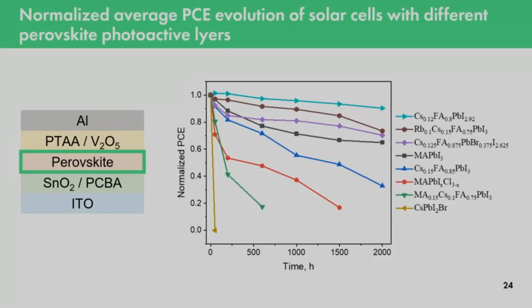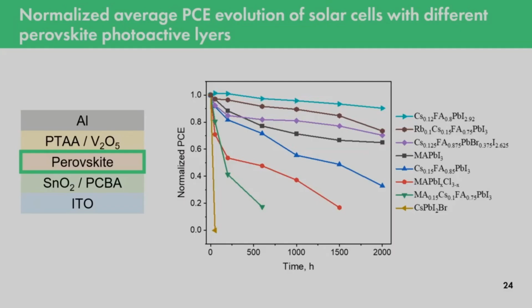Thank you for this question. Actually, these two materials, which are really separated in this rating, have a very drastic change in their chemical composition, because as you can see, the bottom one, cesium 0.15, then formamidinium 0.85, lead iodide 3, is a completely stoichiometric material, which fully corresponds to the formula ABX3. And if we look at the top one, it's cesium 0.12, formamidinium 0.8, and then lead iodide 2.92. This material is non-stoichiometric, as there is some excess of lead iodide compared to all other components.